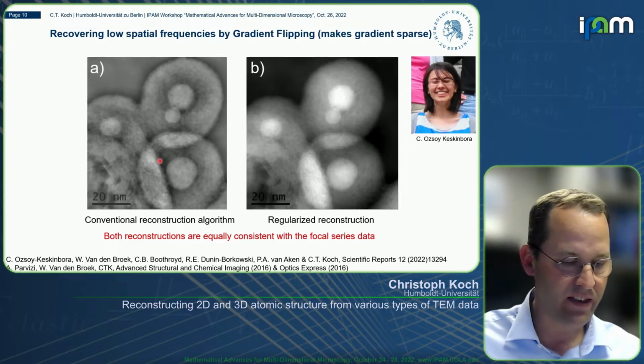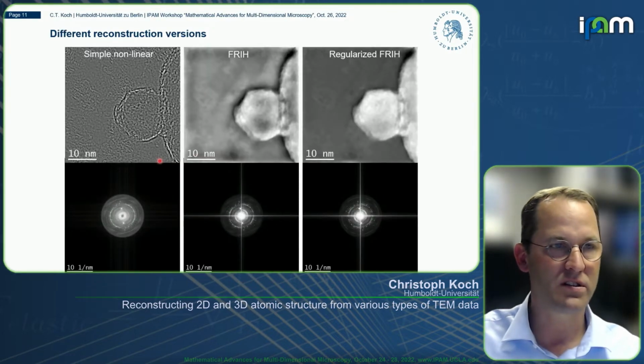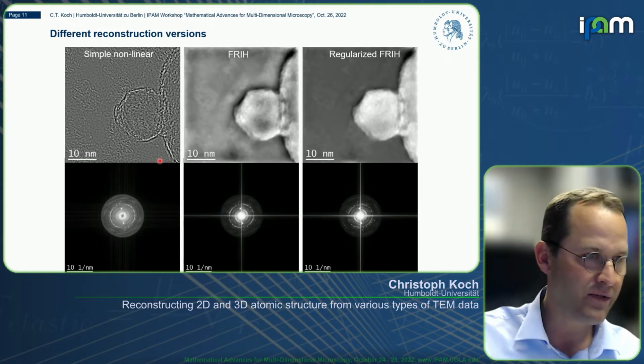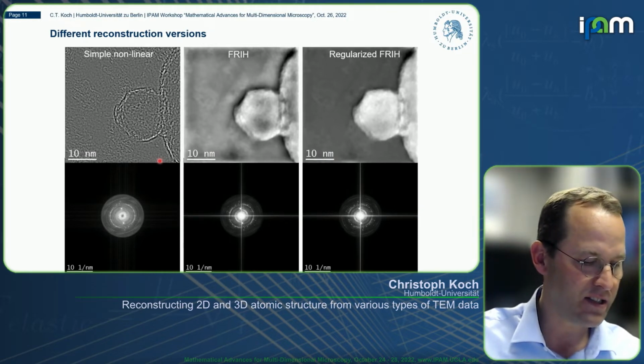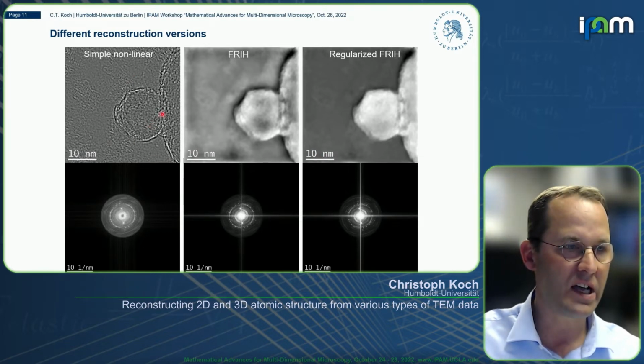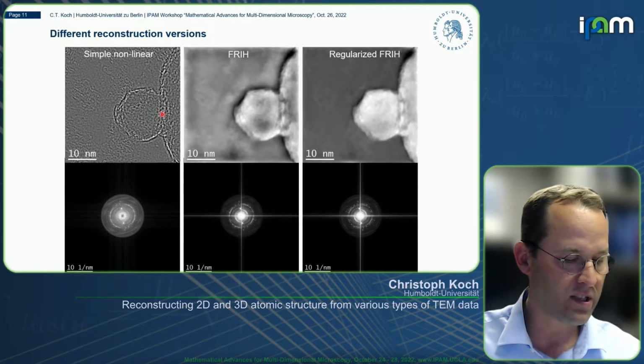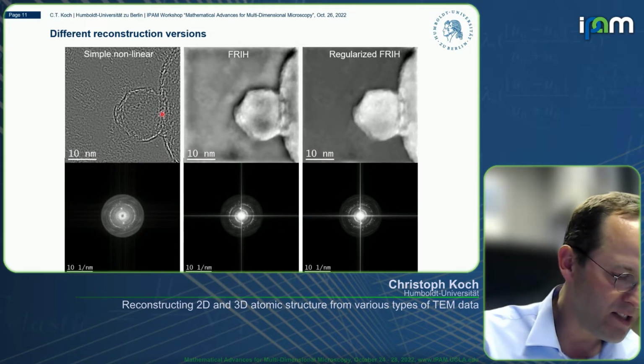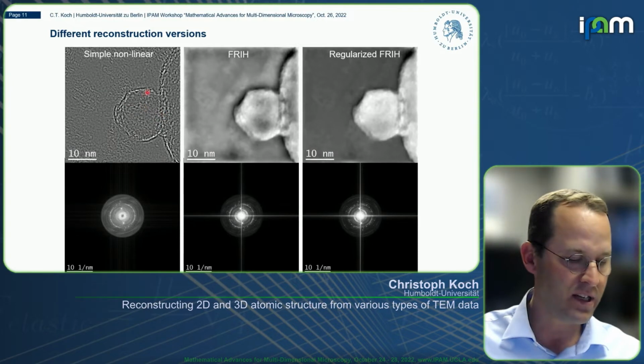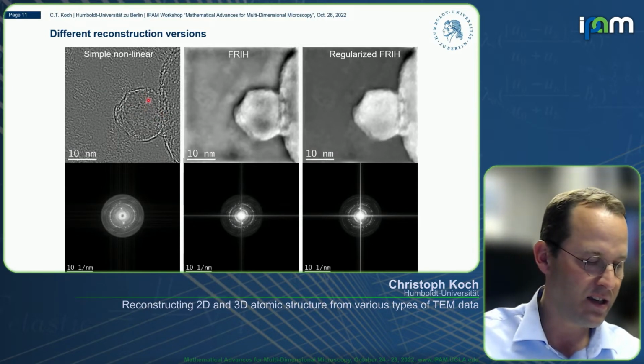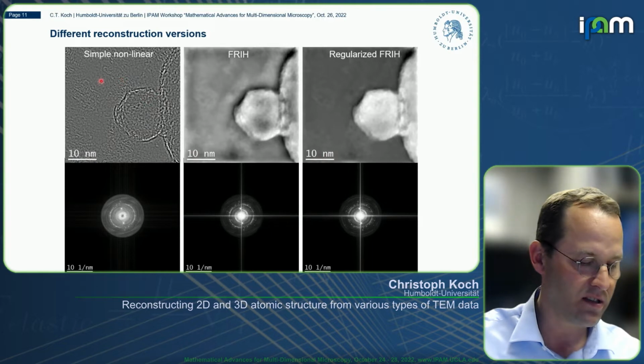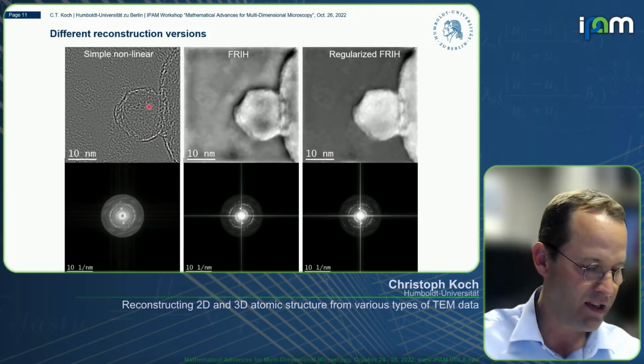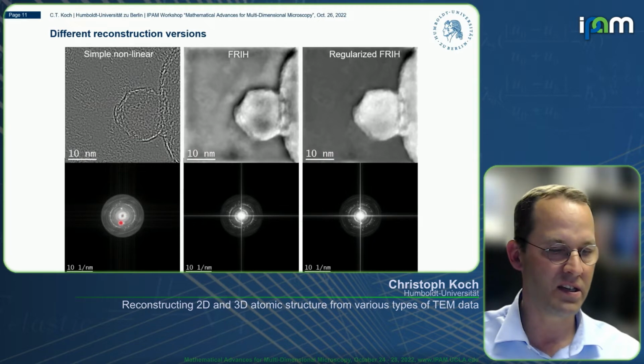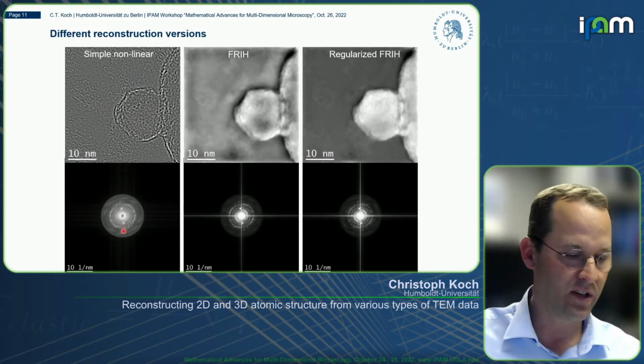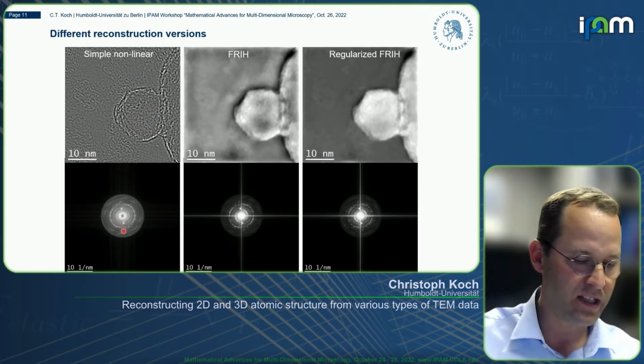And this is just another example at atomic resolution, because of course this talk is about atomic structure. On the left-hand side, you can see a simple nonlinear reconstruction algorithm that reconstructs the phase from a focus series. You can see these lattice planes nicely, and this is what many people are happy with. But what is missing is that the low spatial frequencies are not in this at all. You can also see this in the Fourier transform. There's actually a black hole in the center, which indicates that low spatial frequencies have not been reconstructed at all.